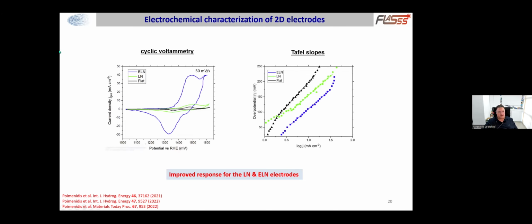Also, typically in our results, we do electrochemical characterization. As you can see with the cyclic voltammetry on the left, looking at the current density produced by the metallic electrodes versus the applied potential, we can see with the green curve and with the blue curve that with every step of nanostructuring, we have more and more production of current density. So the behavior is becoming better and better. The same thing is observed when looking at the overpotentials and the Tafel slopes here.